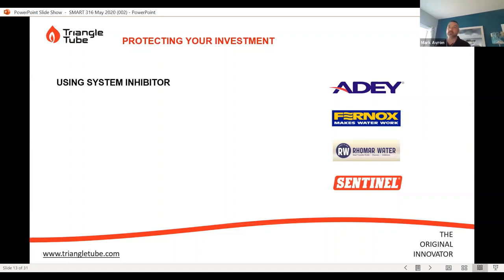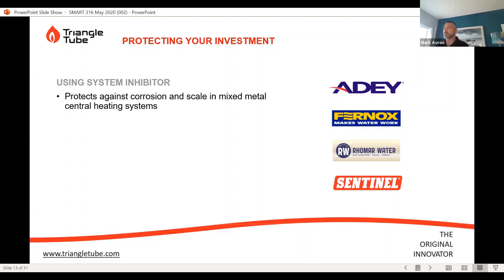Under normal conditions, it's a closed loop system. We're getting air out of the system. There's not an issue. One protective measure that you can take for the entire system, for the boiler, for all of your piping, for your heat emitters, everything, is the use of inhibitors in the system. We're pointing out a couple of different manufacturers here, but it's really to protect against more than just oxygen in the system, because these inhibitors can reduce the amount of oxygen in the system. It's part of what they do, but it can also prevent scale buildup, because anytime you've got dissimilar metals in the system, you're going to have galvanic corrosion, and this will help prevent that, so that your ferrous metals in the system don't degrade over a period of time and turn to sludge and magnetite.